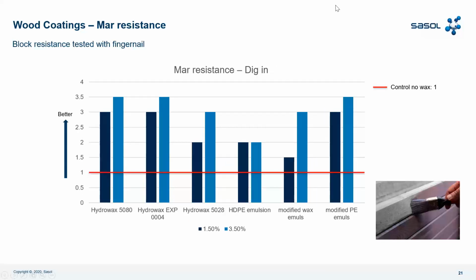Then we have the mar resistance, dig-in. Again, a block resistance test with fingernail, same as before. You need to read the test so that the highest value is better. We have a control, no wax, that achieves 1 in the performance. We have Hydrowax 5080 achieving a similar result to Hydrowax experimental 004 at 1.5%, and then follows Hydrowax 5028.